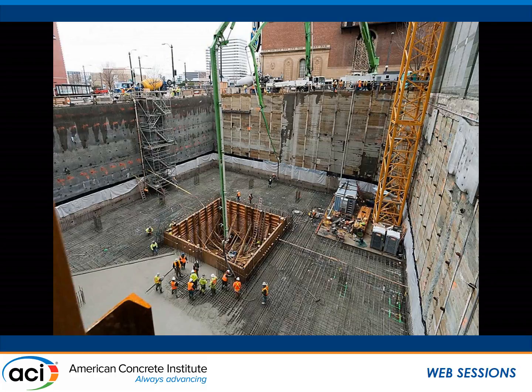The foundations are usually 10-foot thick mass concrete, but in our specification we limited it to a 6,000 PSI mix, and we limited the cement to 400 pounds and told them to substitute fly ash for the rest of it, so you can have a lower heat of hydration. This is the core in the middle.